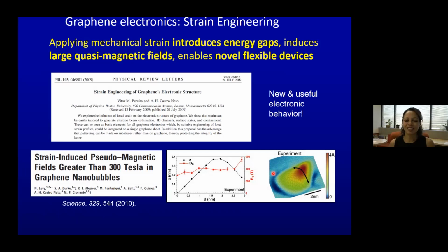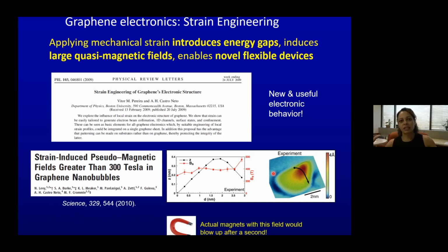Somehow, even without applying an external field, the electrons behave as if they're in a 300 Tesla field. And 300 Tesla is really large. Just to give a sense of scale, in the lab, you might get a field of 20 Tesla if you're willing to pay $300,000 for a magnet. An MRI magnet might be 16 Tesla. And I think the largest field that's been shown on Earth, where you put a huge current in it and then the magnet blows up, is something like 120 Tesla. That's high enough to make a magnet blow up. So 300 Tesla, to see electronics at that scale is a really impressive and interesting thing. But this was done with scanning tunneling microscopy, not across the device.